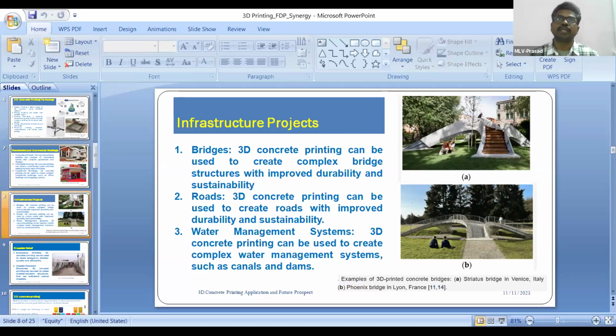Basically, why I am giving this much detail is because, in the preparation of this 3D printed additive, if you are not preparing on your own and do not have control over the workability and thickness of the layer, even 6 mm to 10 mm only we will add initially. And even without fibers, when it is coming out from the nozzle tip, it should flow smoothly, just like how our pen flows. There should not be any boulders or any particle size greater than your nozzle size. Otherwise, it will get stuck. So all these precautions we have to take when we prepare.